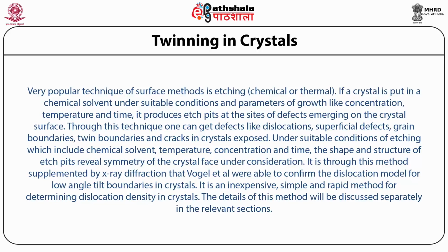Under suitable conditions of etching, which include chemical solvent, temperature, concentration, and time, the shape and structure of etch pits reveal symmetry of the crystal face under consideration. It is through this method, supplemented by X-ray diffraction, that Vogel et al. were able to confirm the dislocation model for low-angle tilt boundaries in crystals. It is an inexpensive, simple, and rapid method for determining dislocation density in crystals. The details of this method will be discussed separately in the relevant sections.